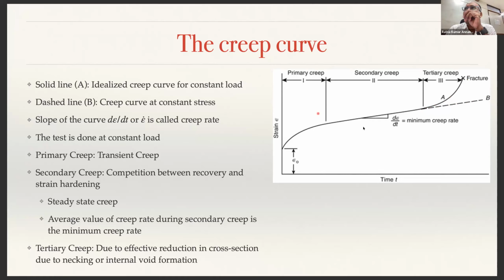Now, the slope of this curve, d epsilon by dt, is what we call epsilon dot or creep rate. This test, as we have said, is done at constant load. This primary creep is what we call transient creep, wherein the creep rate is evolving. And the secondary creep will have a constant creep rate. This happens between recovery and strain hardening, and this is also called steady state creep. That means the creep rate is maintained constant.